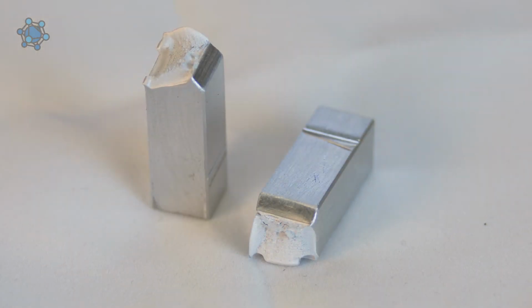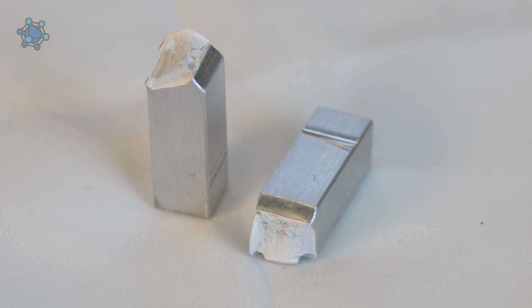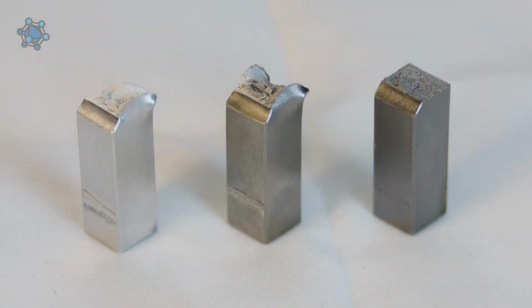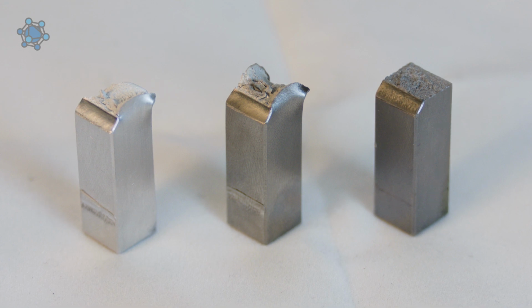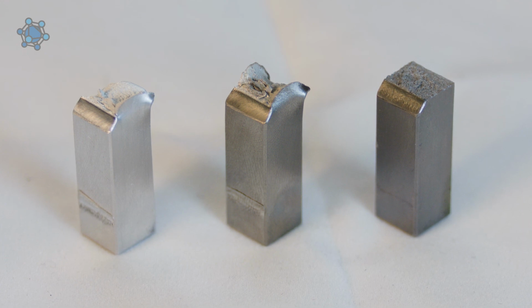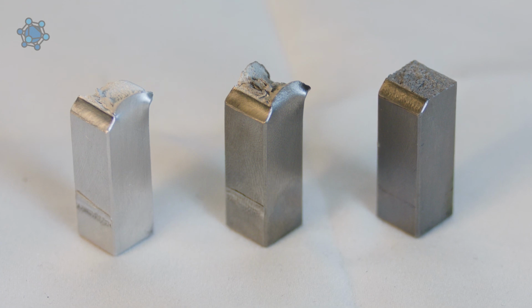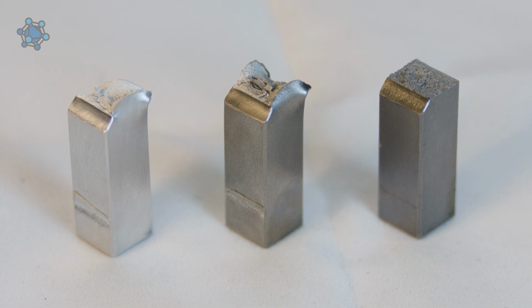The specimen once again broke in two pieces. In a direct comparison of the three samples, you can see the similarity to the stainless steel fracture, shape and surface, and the difference to the C45s. So the value of the impact energy alone is not sufficient to judge the toughness or ductility of a material. The fracture shape is also important. This is especially the case when comparing different material groups, as we're doing here.